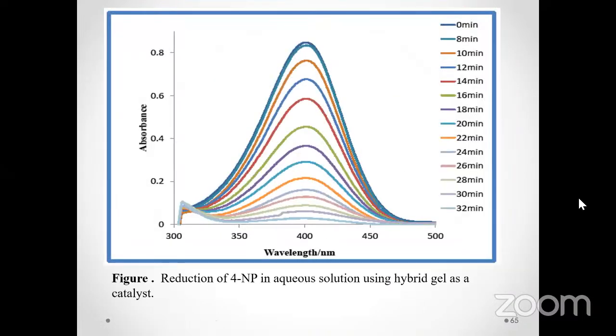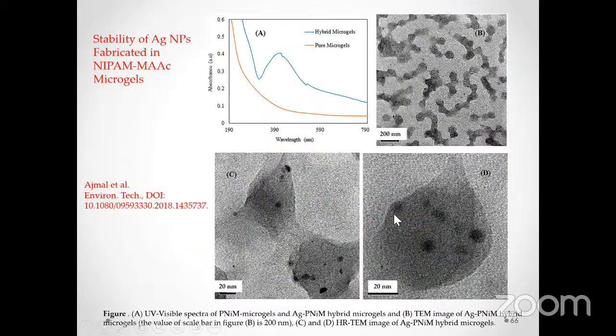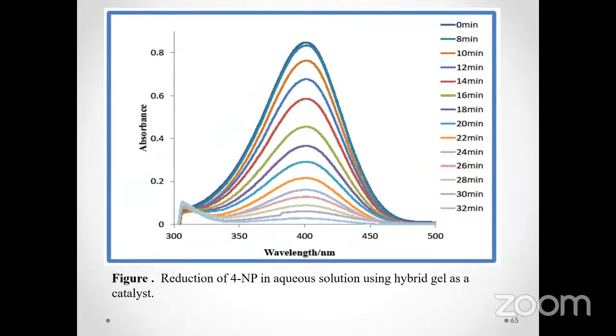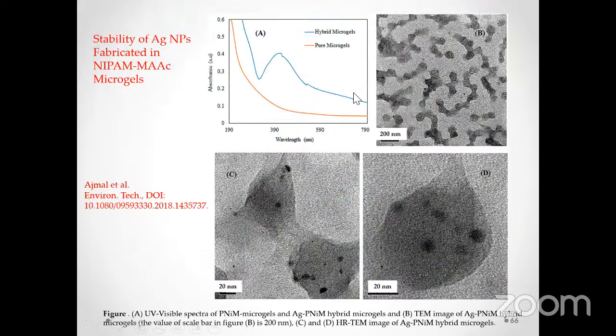And again, this system also had catalytic activity, which was observed in the reduction of 4-nitrophenol. The formation or synthesis, or the existence, of silver nanoparticles in another system was also confirmed by this optical response: when we have only hydrogel, there is no optical response. But when the silver nanoparticles are fabricated in the same hydrogel system, then the composite system gives an optical response.